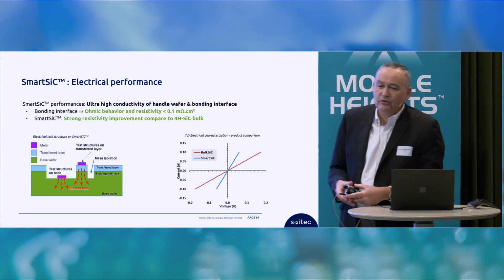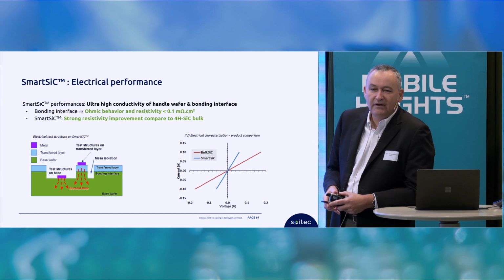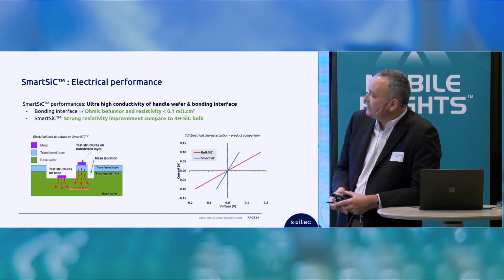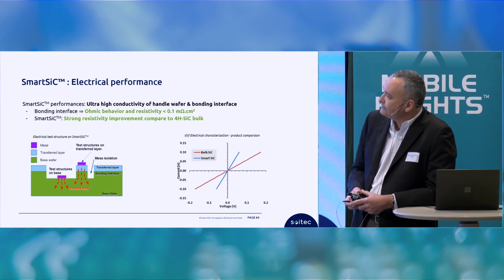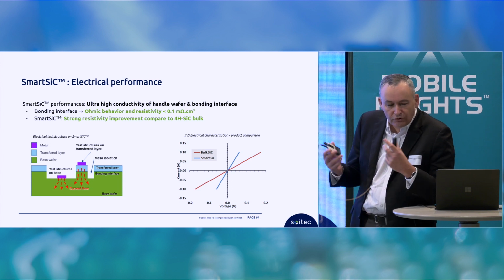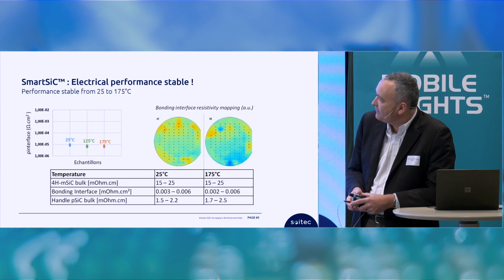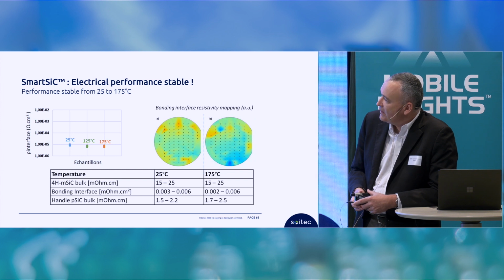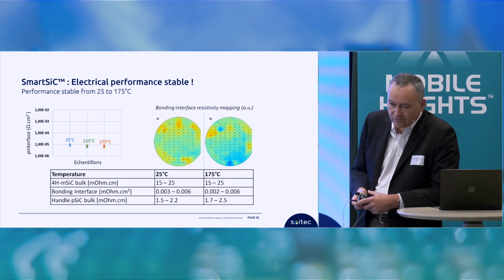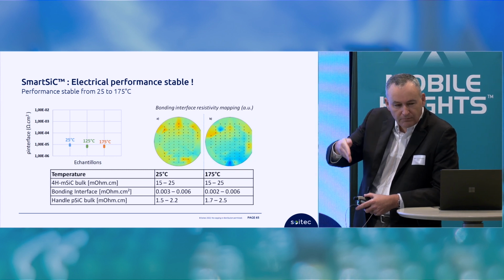When you combine a mono SiC, a perfectly conductive bonding layer, and the handle wafer, the bonding interface has ohmic behavior, a strong resistivity improvement. We can monitor, of course, the total substrate electrical resistivity, and we confirm also this electrical resistivity is stable, whatever the temperature, from room temperature.